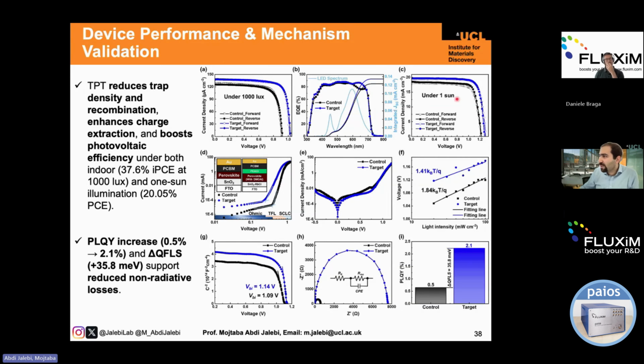And for the one sun as well, you can see that we have significantly lower hysteresis, enhancing the JSC, and specifically for VOC, a significant enhancement for the wide bandgap perovskite, which is reaching over 20%. And the indoor PCE, or power conversion efficiency, is almost 38%. EQE also shows that the spectral response of the devices is matching, and the currents from EQE match the current that we measure using our solar simulator. And we also utilize Paios from Fluxim.